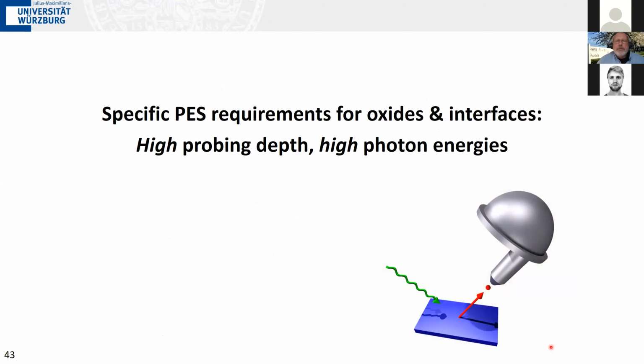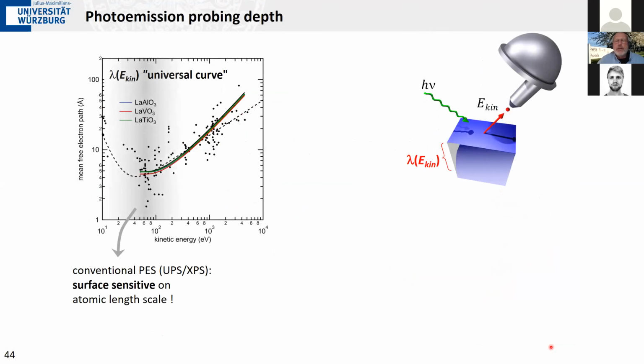There are a few things that are particular about photoelectron spectroscopy of transition metal oxides, and this concerns high probing depth and high photon energy, and this is covered here. This is the universal curve that I have shown you before. These straight lines are actually calculated mean free paths for a range of transition metal oxides. And you can see, again, this is very surface sensitive, but in oxides, you very often have a problem with surface sensitivity.